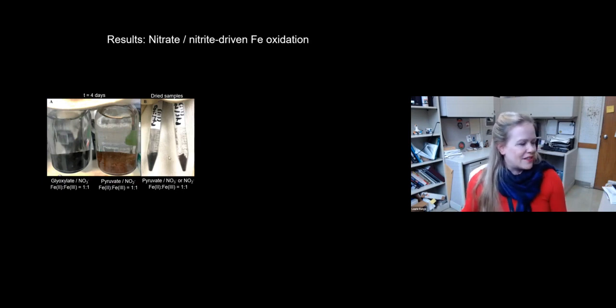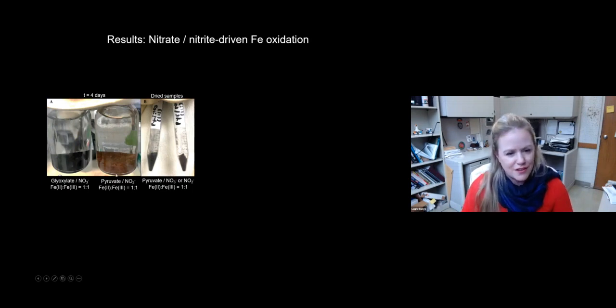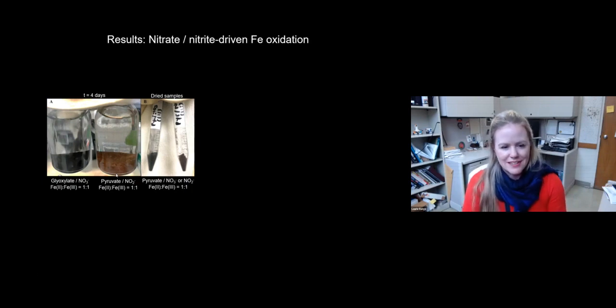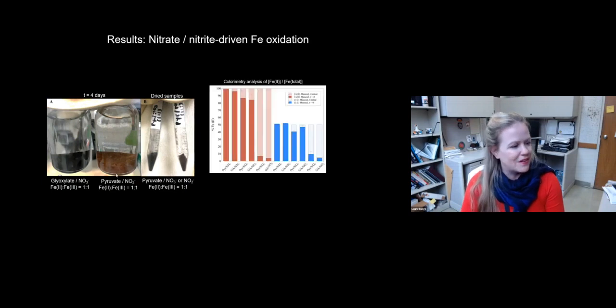And so obviously you can see that the pyruvate nitrite sample has now turned to a bright orange color. It looks a lot like a ferric oxyhydroxide. And then if we take those dried minerals, dissolve in acid, and then do a colorimetry treatment that basically measures the amount of Fe2 to Fe3 in that solution, which then you can backtrack and say that's how much is in the mineral. So we can track oxidation state as a function of time.